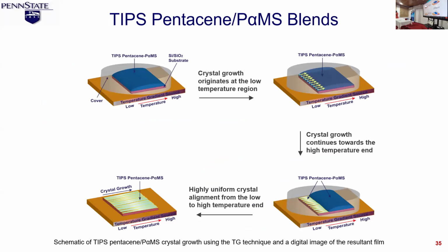Again, use the same temperature gradient method. The biggest difference was that I mixed the TIPS pentacene, which was the semiconductor, with the polymer. Now the polymer is not conducting. So then you think, well, if you're going to mix a semiconductor with a non-conductive material, would the mobility not go lower? We'll see why they actually improve their mobility.